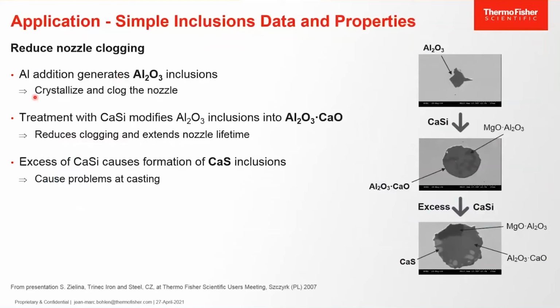When aluminum is added for deoxidizing the steel, there is generation of aluminum oxide inclusions. This inclusion will crystallize and clog the nozzle. Now you have an example of an aluminum oxide inclusion. So steelmakers normally perform some steel treatment. They add calcium compounds to modify the aluminum oxide inclusion into calcium aluminate inclusions that are liquid in the liquid steel and will move to the slag.